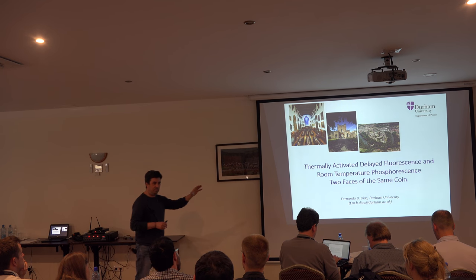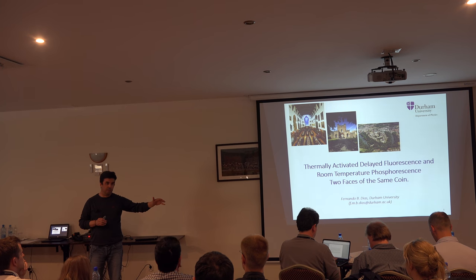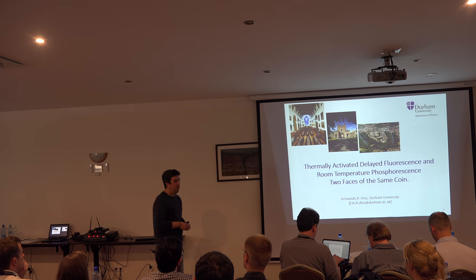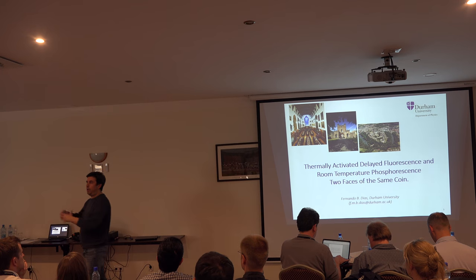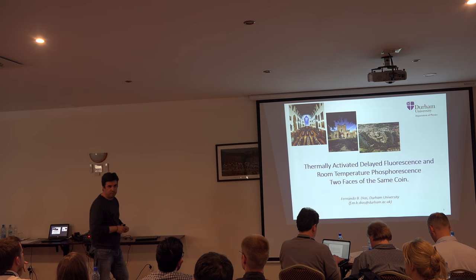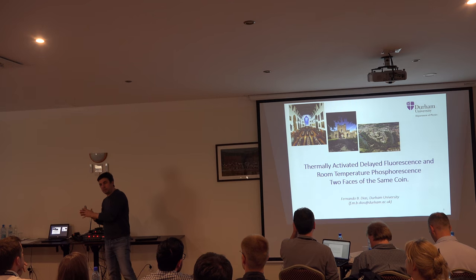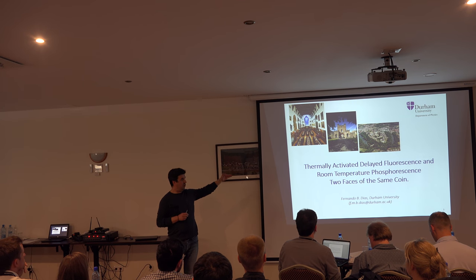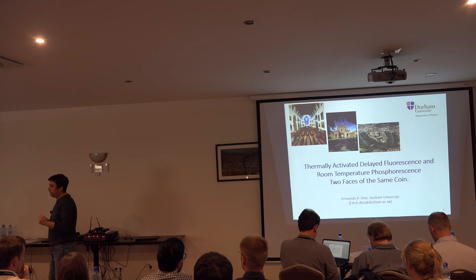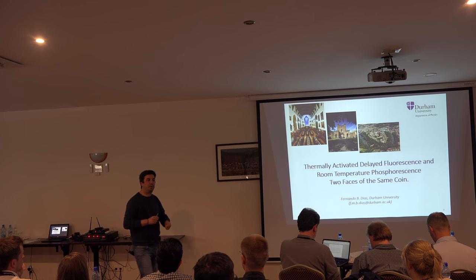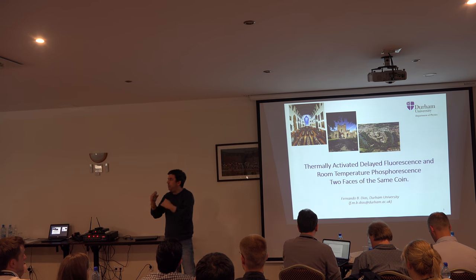In devices, at the moment, these materials are not relevant because the lifetime is long and you suffer a lot of quenching. There is one paper from the Adachi group on afterglow OLEDs where room temperature phosphorescence is used, with efficiency maybe below one percent. When we have room temperature phosphorescence, we are learning about the inter-system crossing process, and if we learn about that, we also learn about the reverse process, because the mechanism should be the same.